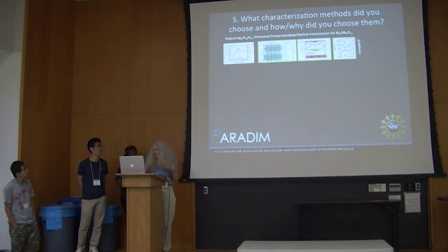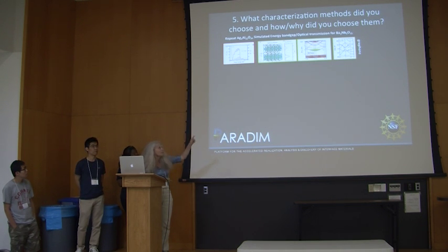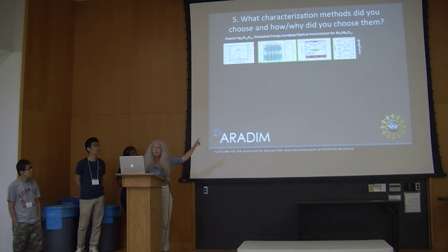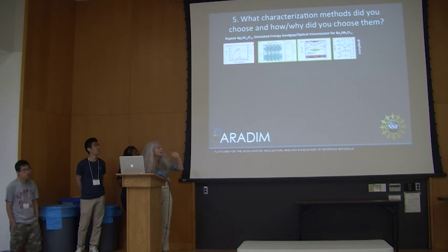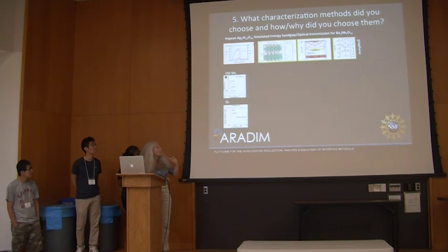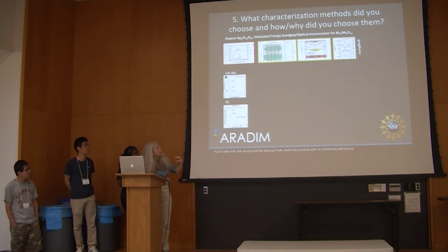The very interesting properties include a wide optical band gap and an electronic structure that suggests that there is a 2D electron gas present, and what I put on the end there is a known 2D electronic band structure, graphene. If you compare those last two, you can see the similarities. So the first thing to do would be to confirm experimentally the properties, if they hold up by theory, of good optical band gap. One could do that with UV-vis. I'm also familiar with photoluminescence.